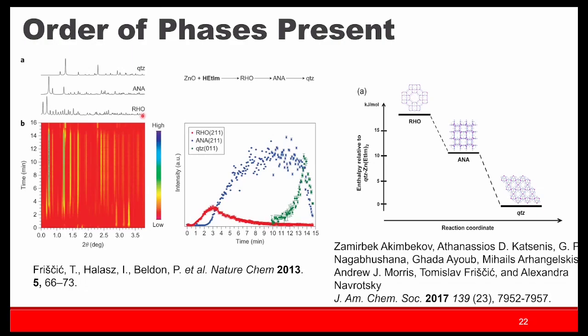And this is actually, in terms of behavior, quite typical of what we see with a lot of milling reactions. And to follow this up, this is not work that I was directly involved with, but came out of the Friščić group a few years ago. When we did these X-ray diffraction measurements, again, in this case, making a ZIF MOF, so this is with ethylimidazole and zinc oxide, we noticed, again, we get this stepwise progression of different phases happening. In this case, the progression is known as the RHO phase, the ANA phase, and then finally the QTZ phase.